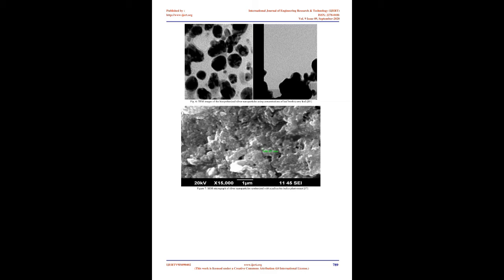Hence, polymeric compounds like polyvinyl pyrrolidone, PVP, polyethylene glycol, PEG, poly(methyl methacrylate), PMMA, poly(N-isopropylacrylamide), NIPA, and poly(methacrylic acid), PMAA, were used as capping or stabilizing agents for synthesis of AgNPs. Khatoon et al. 66 synthesized colloidal AgNPs by using NaBH4 as reducing agent and trisodium citrate as a stabilizing agent. Different stabilizing agents like gelatin, polyvinyl alcohol, PVA, and polyvinyl pyrrolidone, PVP, were used by Shahar et al. 67 to synthesize colloidal AgNPs.